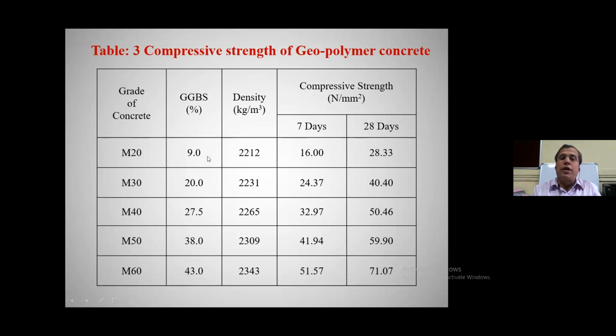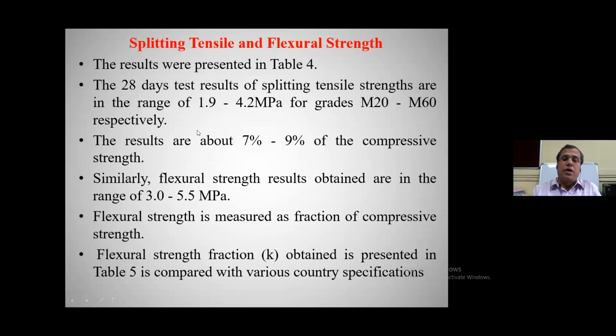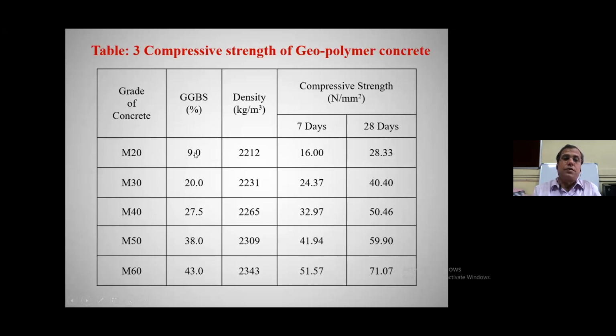When you are taking 20, nearly 30 you should get. 28 means the target 27, 26 point something you are reaching. So that is a fundamental thing that we can remember: when you are designing one particular grade, you should get plus 10 MPa. That is our target strength, and we achieved those target strengths for all grades with these particular replacements of GGBS: M20 is 9.0, M30 is 20%, M40 27.5%, M50 38, and M60 43.